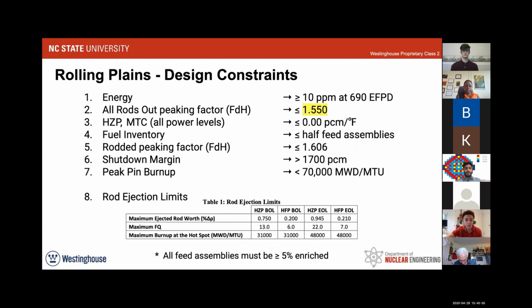So these are the governing design constraints that we use to test each LP and determine whether or not it was viable. The number one is energy, the 10 ppm at 690 equivalent full power days. So that's the overall, it has to meet the cycle length. And then number two was our all rods out peaking factor, our FDH, has to be less than or equal to 1.55. And this constraint was really the one that we shuffled the core around the most and did the most assembly movements to get under that 1.55. It's easy to meet your energy constraint if you just load in a bunch of high enriched fuel, but to meet the peaking constraint was definitely the hardest one.